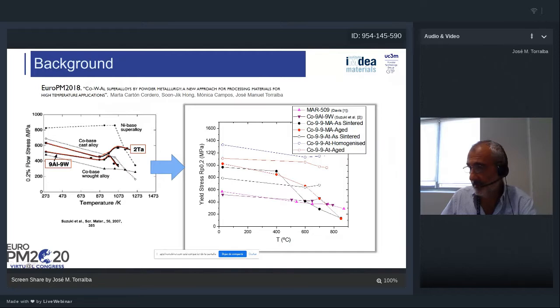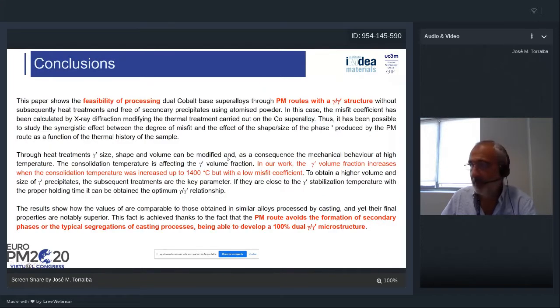So after these results, we can produce some conclusions. And the first one is, of course, the feasibility of the powder metallurgy route to produce gamma prime superalloys with a proper structure to have a good behavior at high temperature. Of course, if we produce heat treatments after the sintering, we can better manage the size and the distribution of these gamma prime precipitates. So in this case, we can in some way tailor the microstructure to obtain good performance at high temperature. So through the heat treatment, this gamma prime can be modified. And of course, as a consequence of this modification, we can modify the mechanical properties at high temperature.